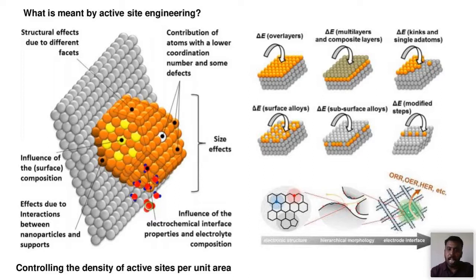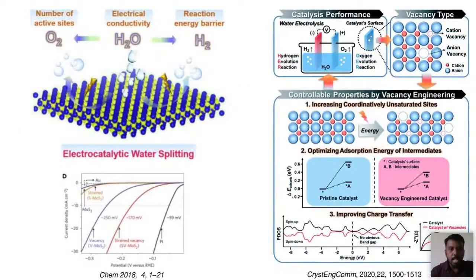Like overlayers or multilayers on a catalyst surface, you can create a single monolayer or multilayer, and based on the number of layers, you can control the surface energy of your electrocatalytic reaction. This can also be done by tuning the electronic structure, hierarchical morphology, and electrode interface. The increase in the number of active sites will lead to an increase in the electrical conductivity, and the reaction barrier can be lowered. For instance, in the case of molybdenum sulfide, if you introduce a vacancy and strain, the activity for hydrogen evolution increases. Different strategies can be used, like catalysis, performance, and vacancy.